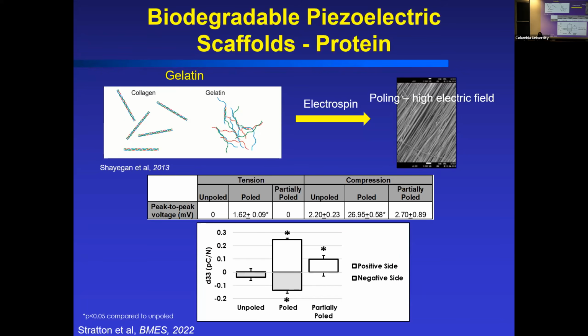But when you take it out of that native state and process it, it loses that property, right? So we can take collagen, denature it, form gelatin. Okay, it's going to lose that piezoelectric property, but we can put it back in and we can vary it, improve the piezoelectric properties such that you can get high amounts of piezoelectric output or lower amounts. So we take gelatin, we spin it, we form these fibers, we apply this high electric field to it, this poling. And we can vary the parameters on the poling. And then what results is this change in electrical output.